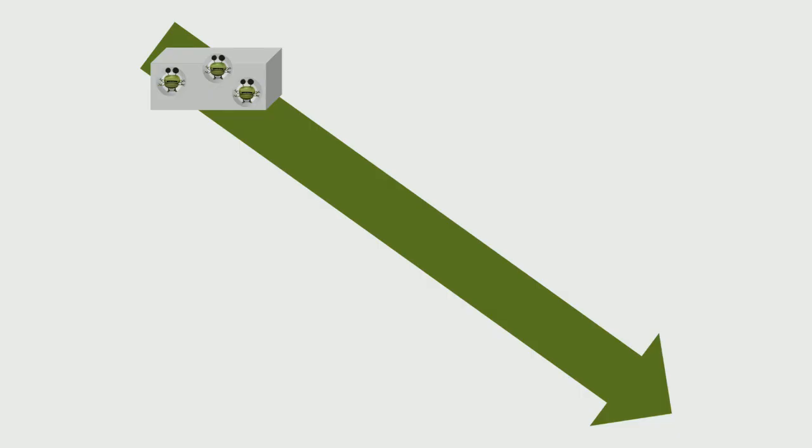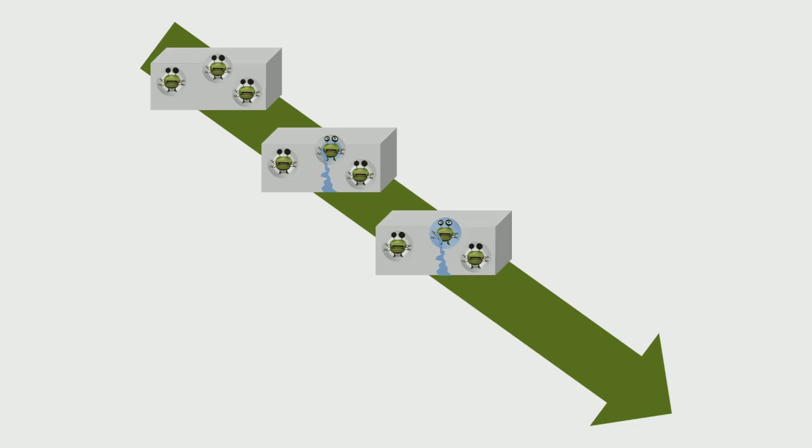Dormant bacteria are embedded inside concrete surrounded by superabsorbent polymers. A crack appears in the concrete matrix and activates the bacteria. The superabsorbent polymers swell and block the crack immediately. The bacteria precipitate calcium carbonate inside the crack, which repairs the crack in a permanent way. The superabsorbent polymers return to their original state.